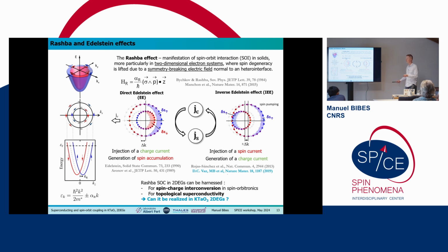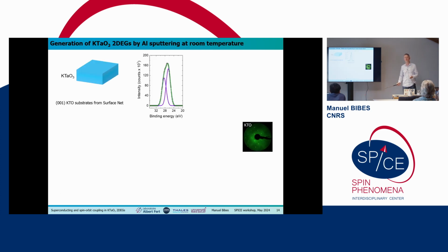But here, for this audience, probably the most interesting part would be to combine the Rashba with topological superconductivity. And so one question that we've been asking ourselves is whether this can be realized in these KTaO3 2DEGs. Okay, so how do we make these samples? One way, as I told you, is to grow a high-quality epitaxial perovskite layer on top of the strontium titanate or potassium tantalate. In fact, we were inspired by a group in Orsay who discovered that depositing a very thin layer of aluminum is enough to create a 2DEG. The mechanism is then different, but at the end of the day, you have a 2DEG. I will explain to you how this works.